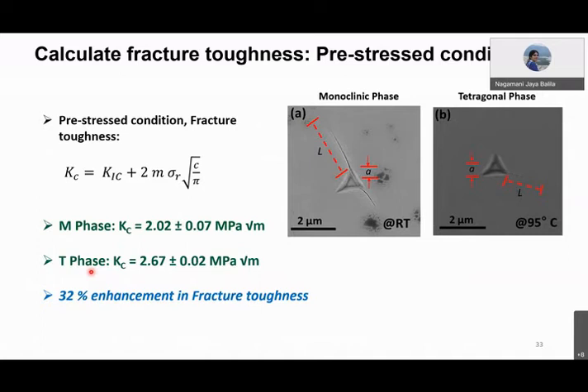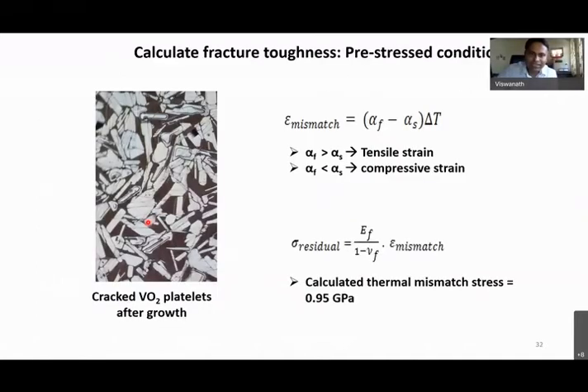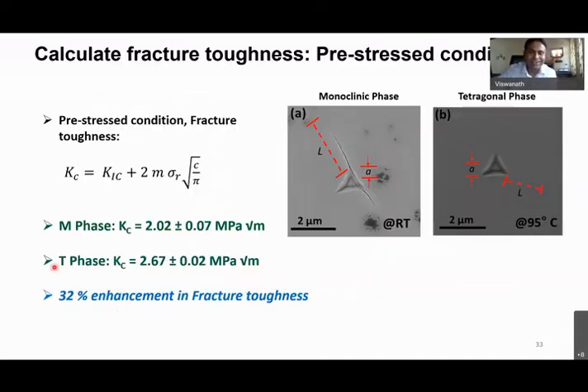You are very correct, very precisely said, because if you look at the residual stress, it is happening due to the growth. So taking the growth temperature and my room temperature, the residual stress is going to be common for both monoclinic and tetragonal phase. So for the tetragonal phase, we have to add the transformation stress as well. So we exactly did that. For simplicity, I thought of avoiding it, but very precise question.